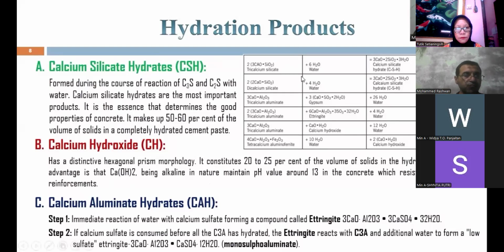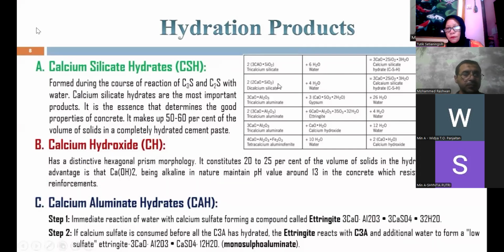For example, C3S, tricalcium silicate: 2 moles of tricalcium silicate react with 6 moles of water and produce 3 moles of calcium silicate hydrate, or CSH, plus 3 moles of calcium hydroxide. 2 moles of dicalcium silicate will react with 4 moles of water and produce 3 moles of calcium silicate hydrate also, plus 1 mole of calcium hydroxide.